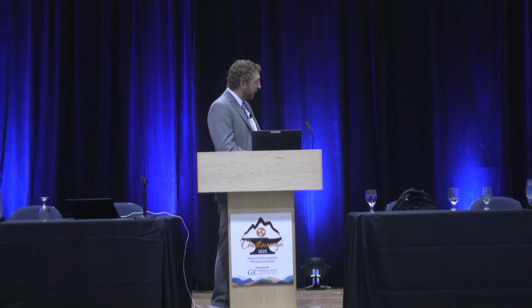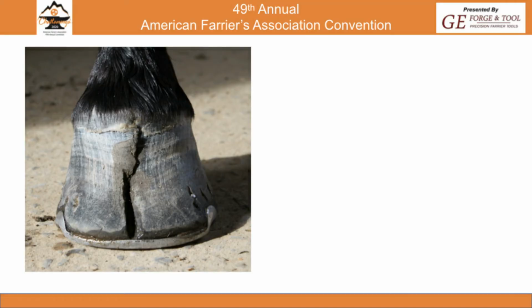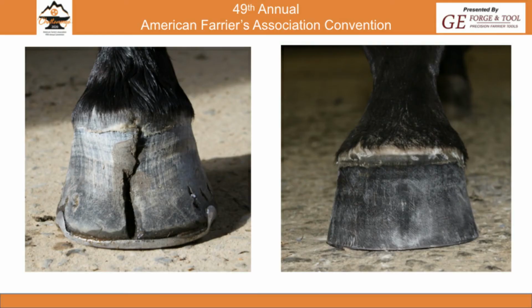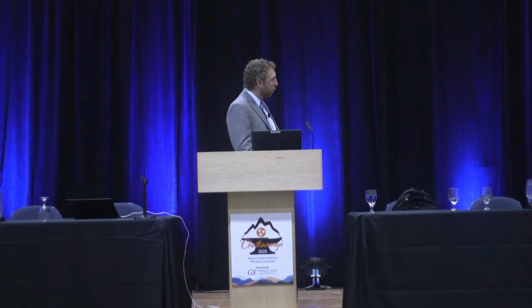And then from there, what I noticed is oftentimes to get this crack to stabilize and get to that foot, the repair composites with the fabrics weren't always strong enough. So again, the quarter crack, not to sound arrogant, is often easy to fix. They're not that bad. But these toe cracks are oftentimes really, really hard to get that first quarter to half inch to grow down and be solid. These are very easy to keep recracking and repropagating.